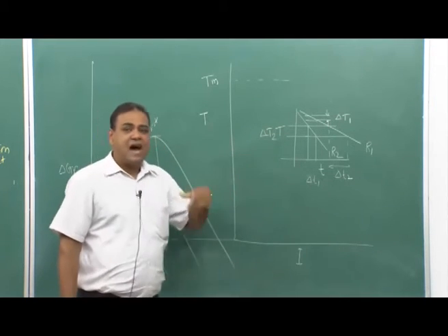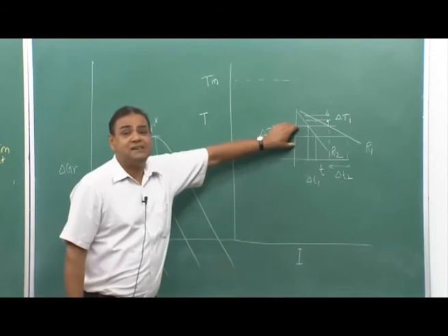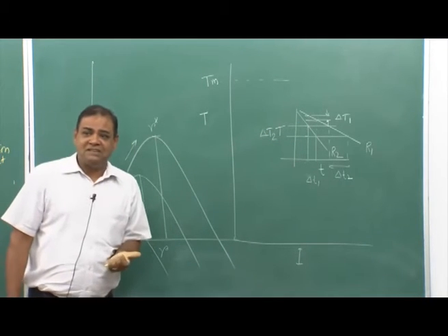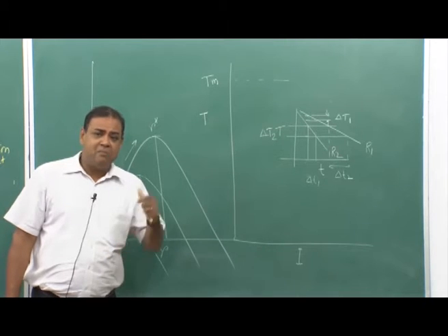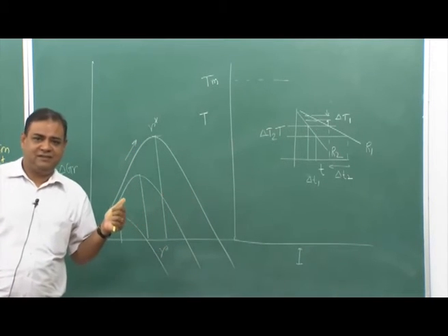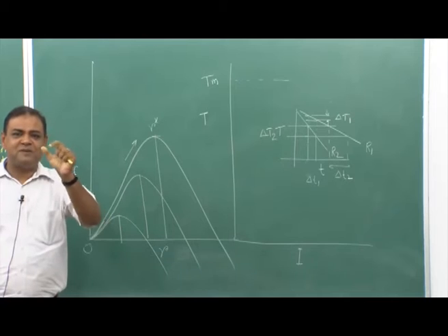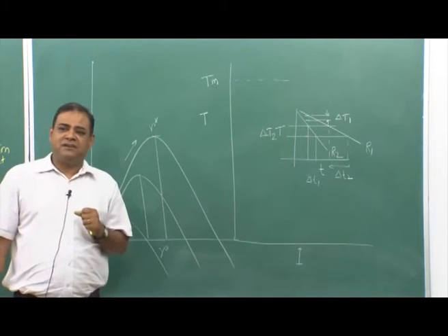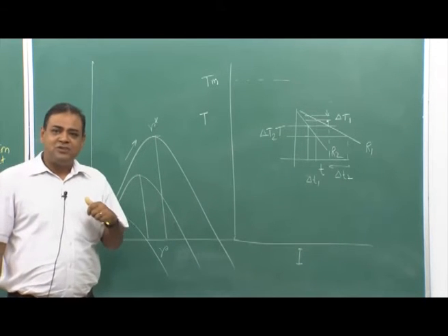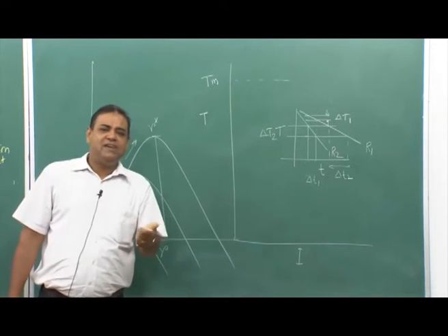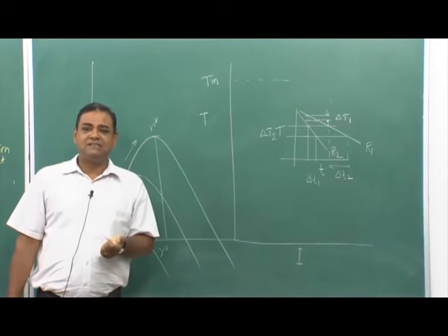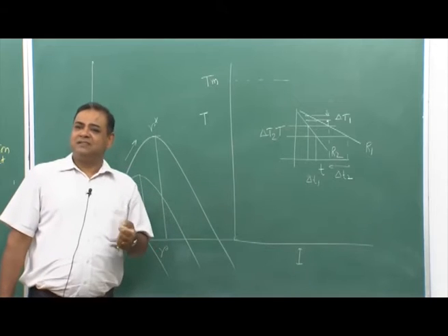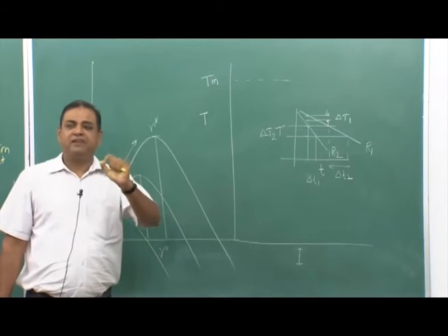Now, if I get higher cooling rate, I am getting higher del T, that means my R star would also decrease. It suggests that I might get finer structure. The size of the sphere would be finer and finer, and I would get very, very fine structure. That also gives a little idea why increase in cooling rate during steel heat treatment gets me very, very fine pearlite, or very fine grain size.